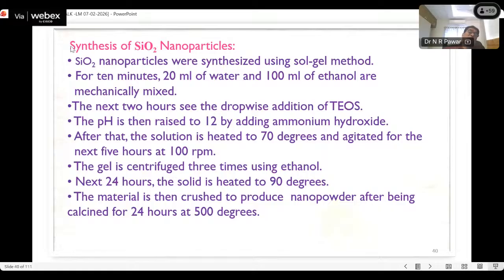Now we have the synthesis of SiO2 nanoparticle. This nanoparticle was synthesized using the Sol-Gel technique. For 10 minutes, 20 ml of water and 100 ml of ethanol are mechanically mixed. The next 2 hours see the dropwise addition of TEOS. The pH is then raised to 12 by adding ammonium hydroxide. After that, the solution is heated to 70 degrees and agitated for the next 5 hours at 100 rpm. The gel is centrifuged 3 times using ethanol. Next, for 24 hours, the solid is heated to 90 degrees. The material is then crushed to produce nanopowder after being calcined for 24 hours at 500 degrees.